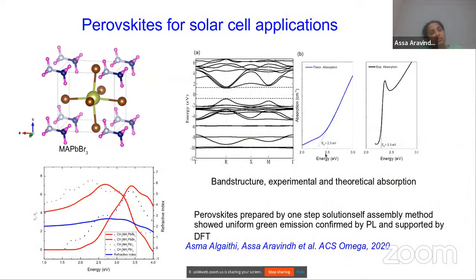Initially, in the first slide, I was showing a bulk material, bulk iron. In the second slide, I was showing a nanocluster. And here it is a perovskite material. I think in the previous talk there was also a mention of photovoltaic perovskites. So there was experimental confirmation of this particular perovskite material, and they were showing a very nice uniform green emission, which was confirmed by PL.